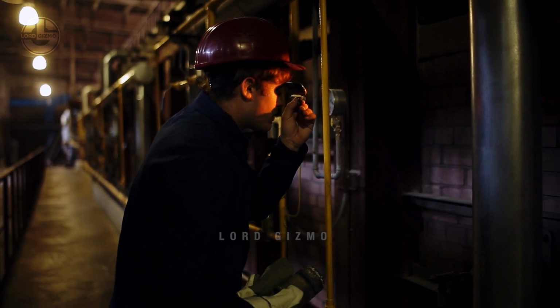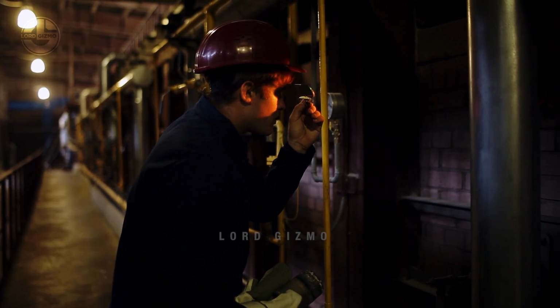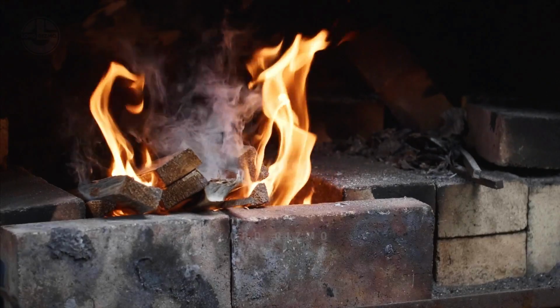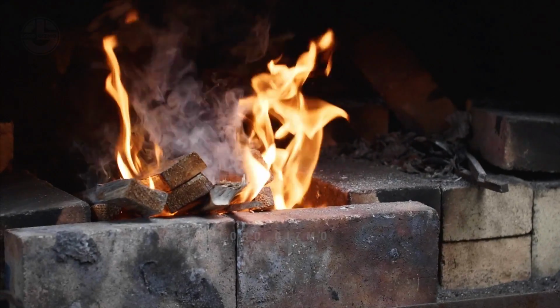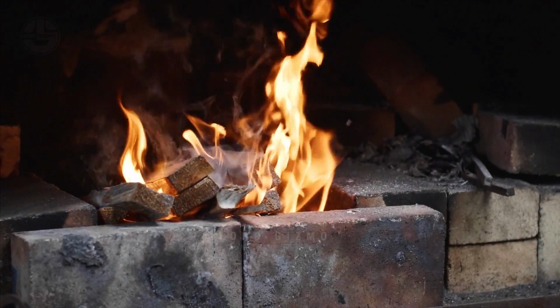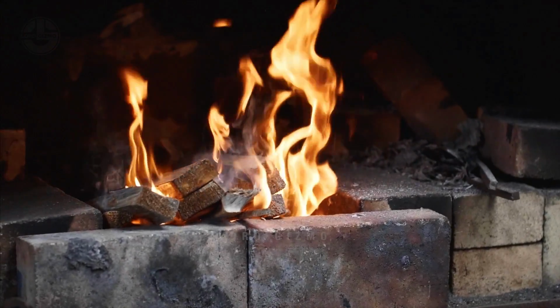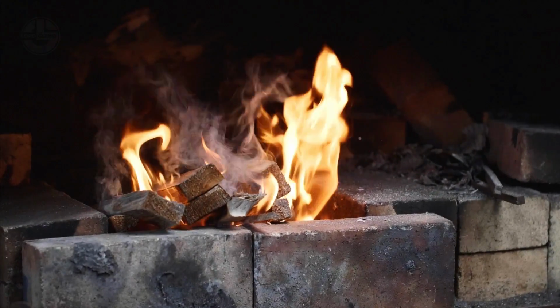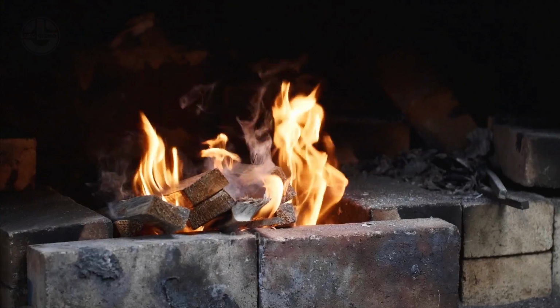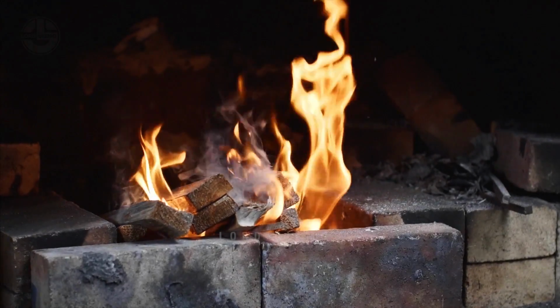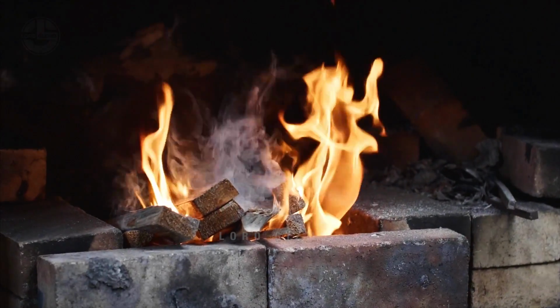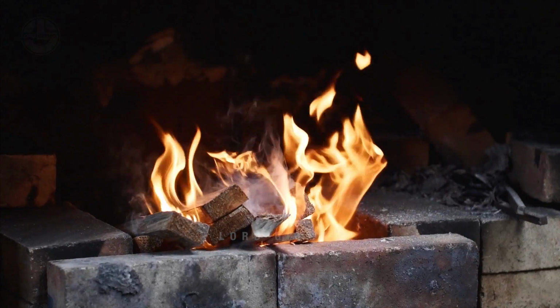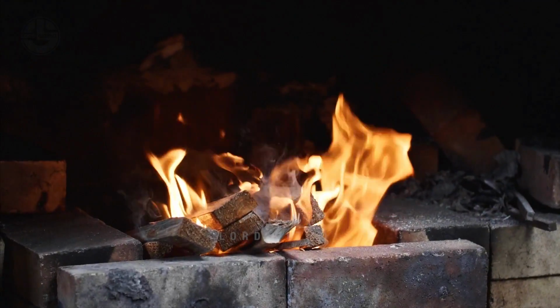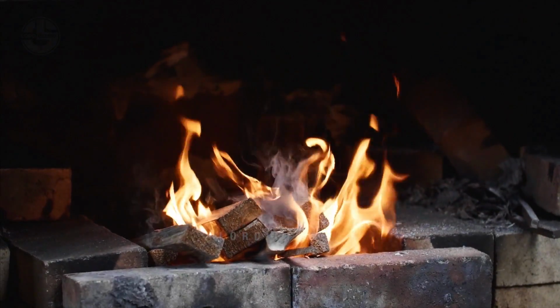The firing process typically involves heating the bricks to temperatures ranging from 1000 to 2000 degrees Fahrenheit, 537 to 1093 degrees Celsius, over several hours. During firing, several chemical and physical changes occur within the bricks. The heat causes the clay minerals in the bricks to undergo vitrification, where they soften and fuse, forming a dense, solid structure.